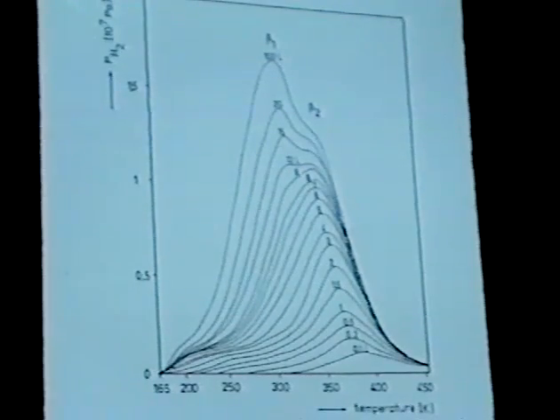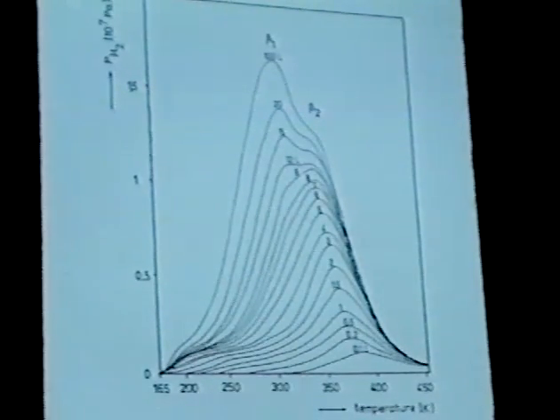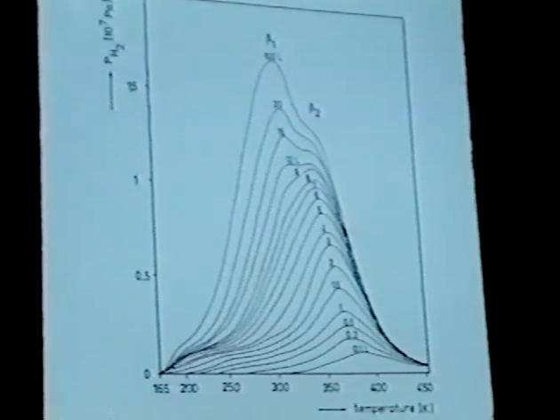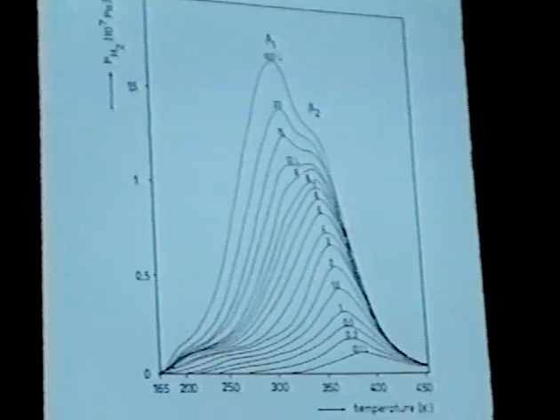The maximum in desorption rate for the beta-1 state occurs at about 300 degrees Kelvin. That means at room temperature we get maximum desorption or removal of this particular atomic adsorption state. In other words, if we perform a hydrogen chemisorption experiment and adsorb at room temperature then purge or evacuate at room temperature, we would tend to remove the beta-1 state because it is reversibly adsorbed. Christman states that at room temperature all of the hydrogen is reversibly adsorbed with a stoichiometry of roughly 0.9 to 1 monolayers — one hydrogen atom per nickel surface atom counting both beta-1 and beta-2 states.